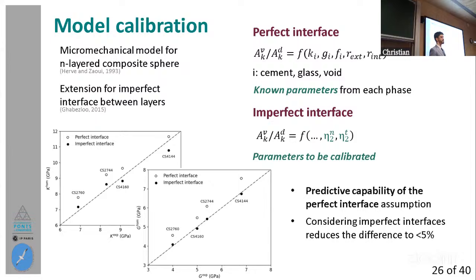Initially the model was modified a bit to account for the presence of the spheres, as using the RVE I showed you before. This was done considering the micromechanical model for a layered composite sphere as developed by Herve and Zaoui in 1993. This is the condition of the perfect interface in which these strain localization coefficients depend only on known parameters, which are the elastic parameters of each material, the volume fraction of each material, and then the external and internal radius of the spheres. We all know that.